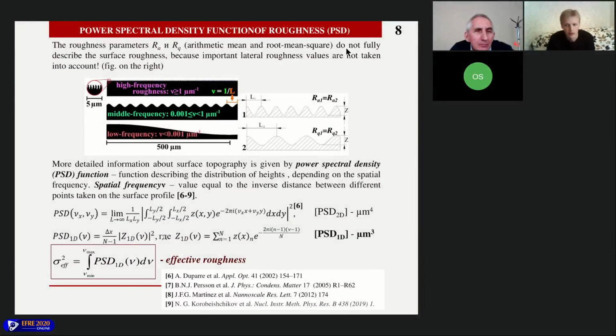Apart from the layer, it is important to consider surface topography. More detailed information about surface topography is given by the power spectral density function of roughness. It is a function describing the distribution of irregularity heights on the sample surface, depending on spatial frequency. The PSD function also allows us to estimate light scattering on an optical surface and calculate the effective roughness of the sample.